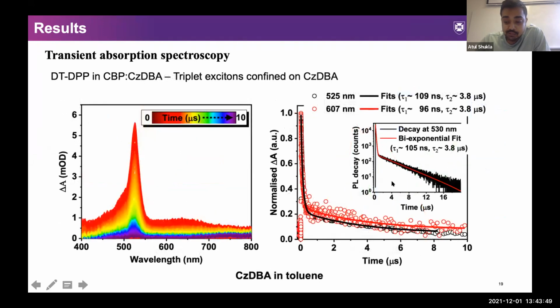When we moved to CZDBA, we found that we cannot really detect any triplet absorption band in our measurements. All of the signals that we had in global fitting showed only a biexponential fit, which technically corresponded with the emission lifetimes, that is, the prompt and delayed lifetimes of CZDBA. The reason behind this can be that the triplet absorption band for CZDBA lies outside the probe wavelength of our instrument, which is good, because in that case, we do not really have much triplet loss in systems where triplets are confined on CZDBA.